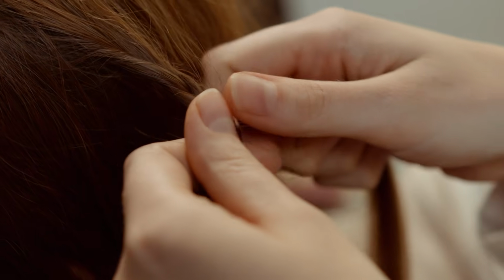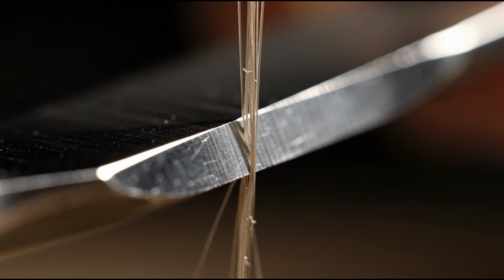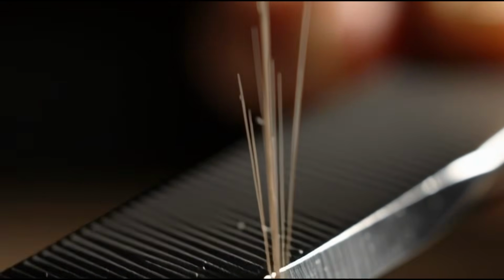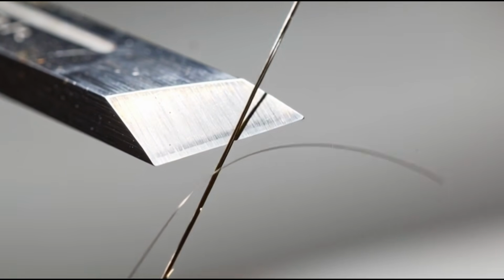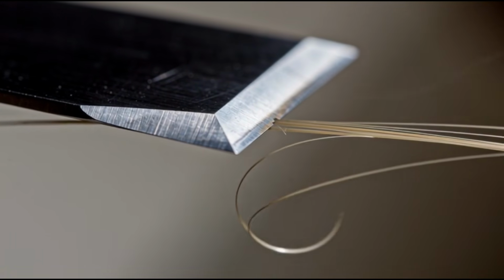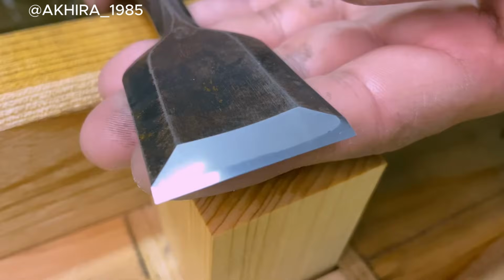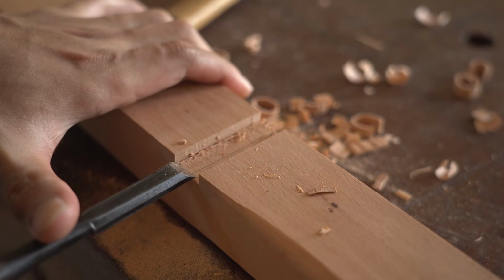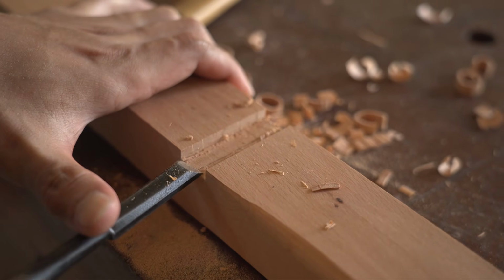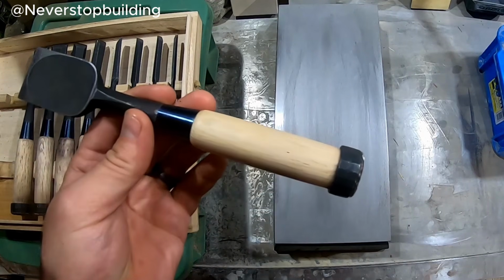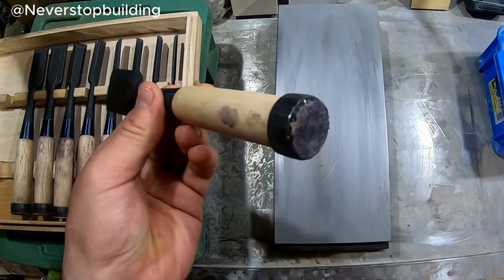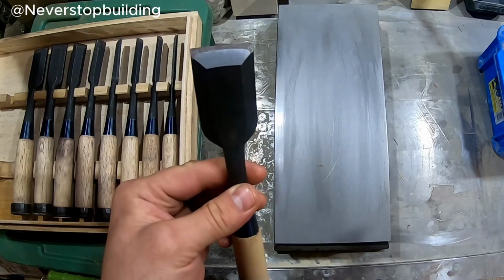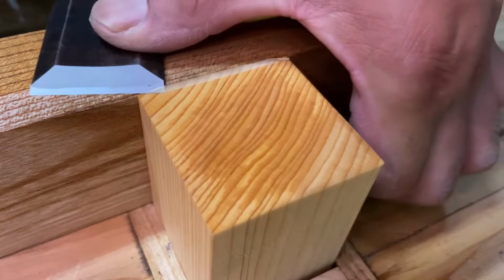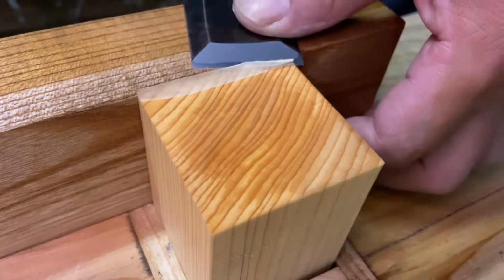The second test is even more demanding. Take a single hair, hold it taut between your fingers, and bring the edge down onto it about halfway along the strand. A properly honed Japanese blade will slice cleanly through with almost no pressure. If it catches, deflects, or won't cut, the edge isn't there yet. This sounds extreme, but remember, these blades are designed to take an edge measured in microns. A hair is about 70 microns in diameter. If the edge can't handle that, it's not finished. I do both of these tests every time I sharpen now, and they've completely changed my standard. I used to think an edge was sharp when it felt sharp on my thumbnail. Now I know whether it's actually performing at the level the steel is capable of.